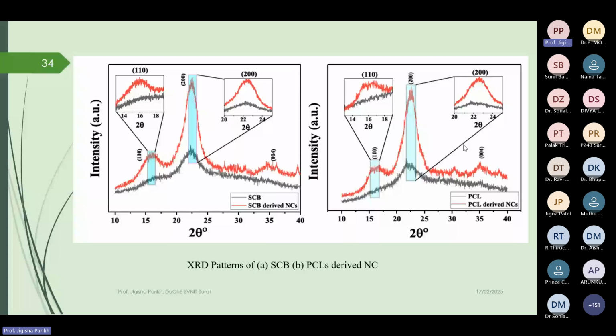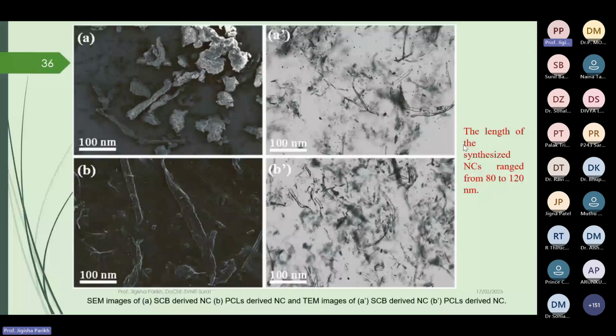Similarly, to identify the structure variation or morphology, we have performed scanning electron microscopy, and TEM images are shown over here. So here you can see that the length of this synthesized nanocellulose ranges from 80 to 120 nanometer. So it is the cellulose nanocrystals which we have obtained, as per the first type of nanomaterial, which was our identified outcome. So we established that yes, we have received that cellulose nanocrystals type of material. From these SEM and TEM images we can identify the length of this.